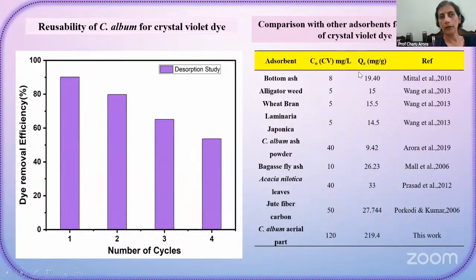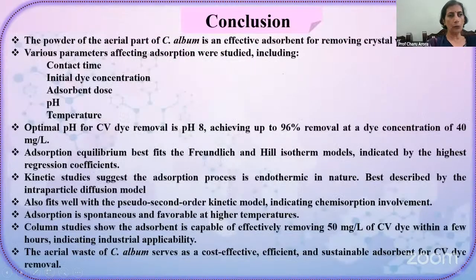This table is showing the comparison of this material with some other adsorbents for removal of crystal violet dye. So you can see in the present study, the removal was 219.4 milligram per gram, which is the highest among the reported values in the literature. Our material is very efficient for removal of crystal violet dye.